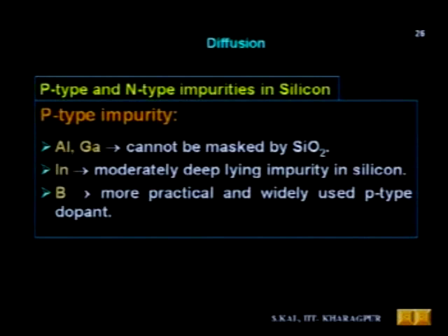Another impurity atom is indium. Indium is never popularly used as a p-type dopant in silicon. One of the major reasons is that indium is a deep lying impurity in silicon. Since it is a deep lying impurity, if you want a very shallow junction near the surface, it will pose some problem, because its diffusion constant may be very large and it is a deep lying impurity in the bulk of the silicon.